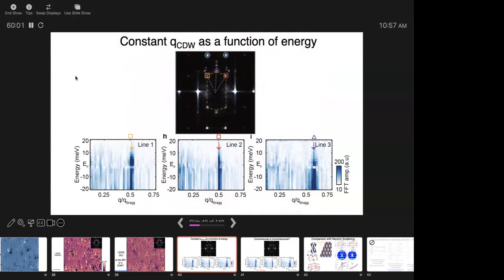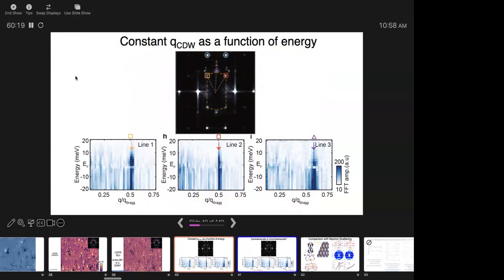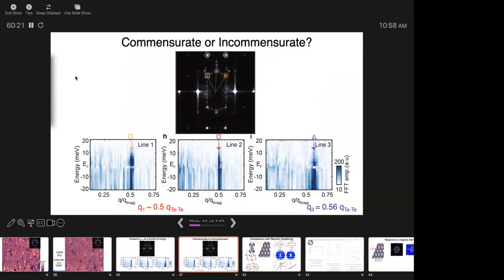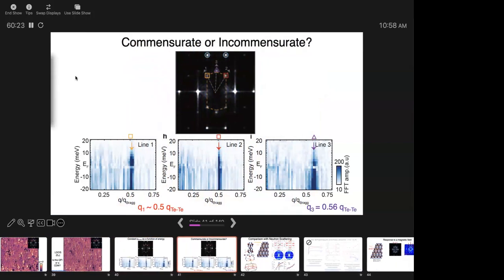This is a line cut in these three directions, with energy on one axis. So this peak is represented by this dark line. You can see as you change energy, this is momentum. So the momentum of this peak doesn't change as you change energy. So all three peaks, the momenta don't change. So this is a charge density wave. And this is what the charge density wave Q is. And even though this is 0.5, it's not commensurate because it's in the wrong direction.